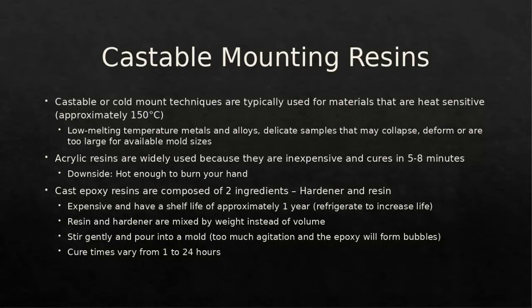If you don't use it a lot, then you do not need a 5-gallon drum of the resin and a 1-gallon bucket of the hardener. When you mix them together, you're going to do it by weight. So you'll measure them by weight instead of volume, and that gives you more accuracy to the ratio. Ratios change. Some call for a 10-to-1 mixture of resin to hardener. Some are 5-to-1, and some are 2-to-1. So it's going to depend on the brand and also the type of resin that you ordered.